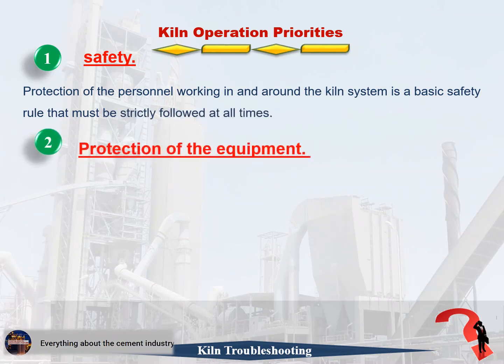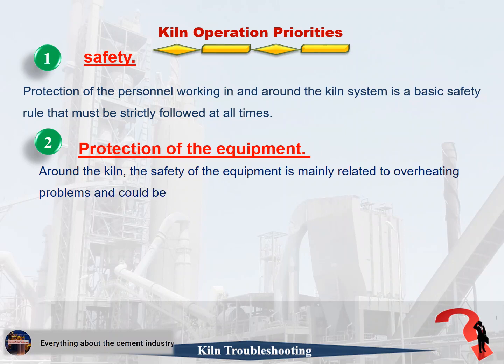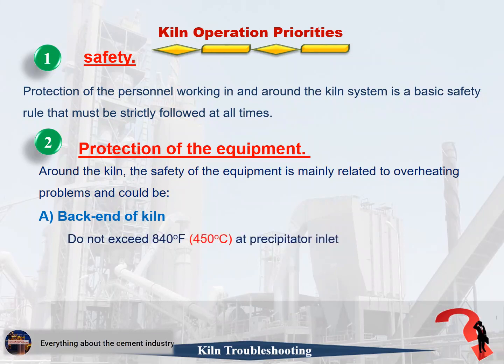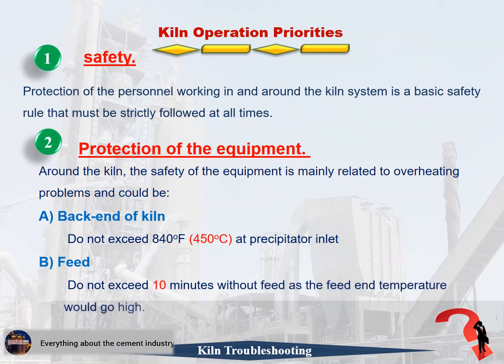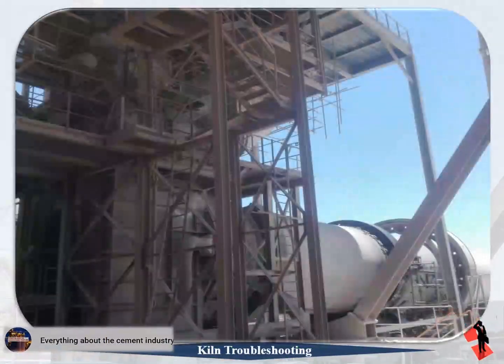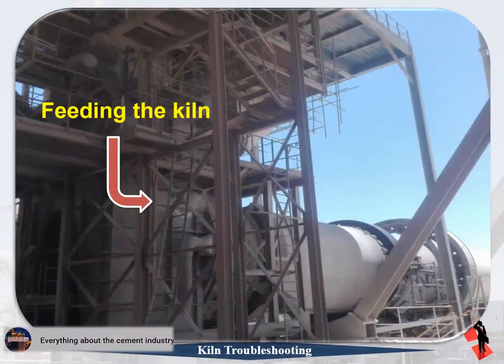2. Protection of the equipment. Around the kiln, the safety of the equipment is mainly related to overheating problems, and could be: A. Back end of kiln. 1. Do not exceed 450 degrees at precipitator inlet. 2. Feed. Do not exceed 10 minutes without feed, as the feed end temperature would go high. This picture shows the inlet of the rotary kiln.